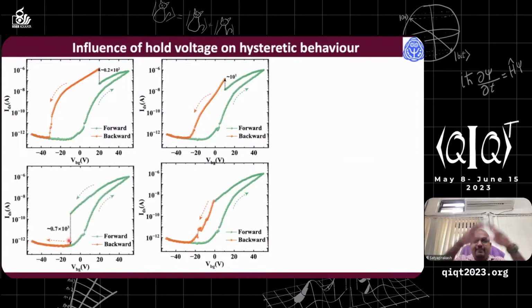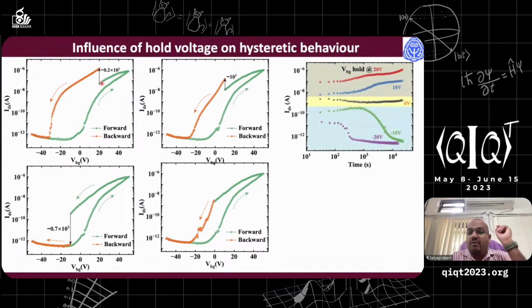And you see a dramatic change in the hysteresis behavior is observed. And as I mentioned, during these 6 hours while we hold the experiment, we are doing another experiment. That means we are doing a transient experiment. We are measuring the time versus the ID, how the current is changing. Once you are at this stage, how the current is changing.